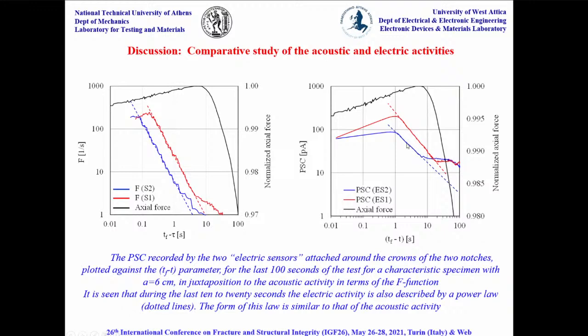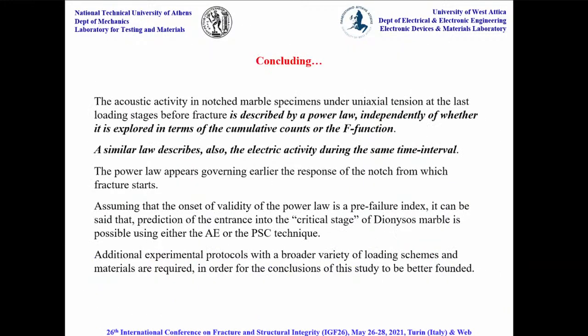And then you can see here the very last seconds before fracture, what the electric sensors described. Again, you can see that during the last seconds, we have a power law that governs the behavior of the material. So if we assume that when this power law starts governing the response of the material, it is a kind of pre-failure indicator, then we can relatively safely conclude that at least for the Dionysos marble, we have a very clear pre-failure indicator, which is provided almost simultaneously by both the acoustic sensors and the electric sensors.